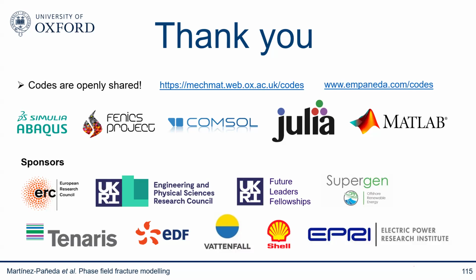Okay. Thank you. Yeah. Well, the group of Wu in China has also championed this method. We have championed this BFGS approach. The problem is well bounded, so the phase field never really evolves beyond 1. Sometimes people show small changes, but I think this is more post-processing extrapolation. So the problem works quite well. What I would say is that convergence is quite good and is quite improved. However, the approach that Wu used and we used is the same.